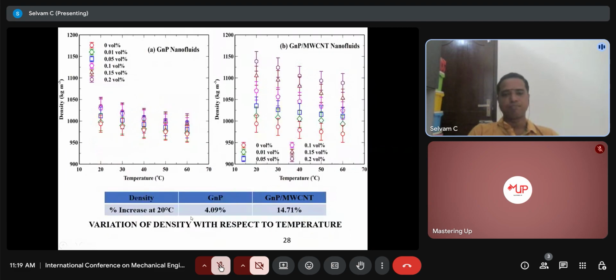And density as per the standard, with respect to temperature, is decreasing, but with respect to concentration, it is increasing. The increment in density with respect to the graphene nanoplatelets is only 4.09%. But when we disperse the graphene and multi-wall carbon nanotube in the base fluid, the increment observed is 14.7%, because the multi-wall carbon nanotube has high density as compared to graphene, like 2.5 to 3 gram per cc. That is why the density increased significantly as compared to GN.